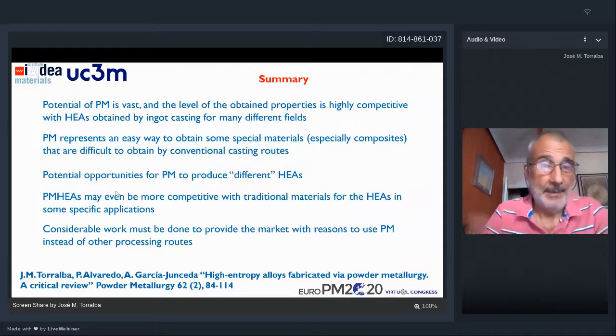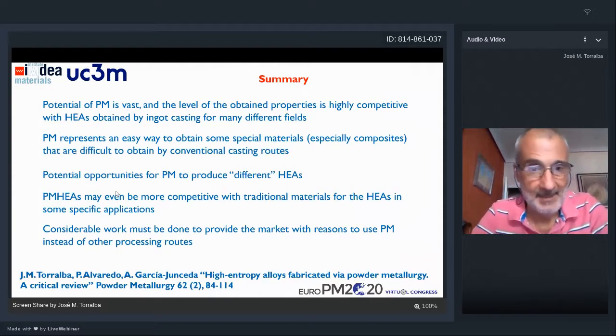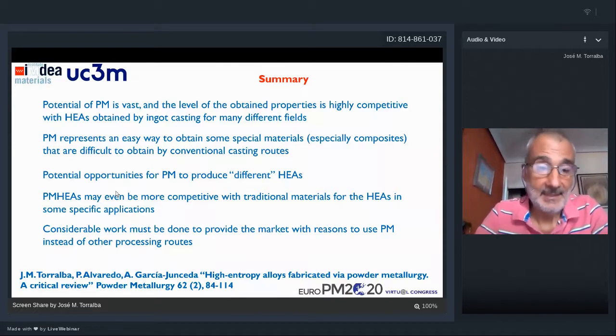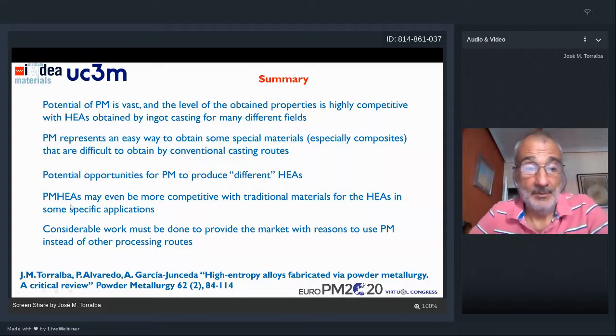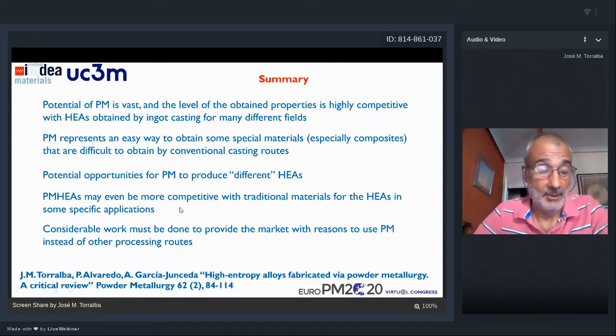So as a summary, I'd like to say that the potential of powder metallurgy is really vast, and the level of the obtained product is competitive with the conventional high entropy alloys obtained by ingot metallurgy, and also with materials that can compete for the same, let's say, niches or the same areas of application. PM represents an easy way to obtain special materials. We have mentioned composites, cemented carbides, and so on. So here we have a field in which a material is impossible to be obtained by alternatives. We have a lot of potential opportunities to produce different high entropy alloys, just in terms of alloying elements. PM even can be considered more competitive than traditional routes for high entropy alloys in some specific applications.